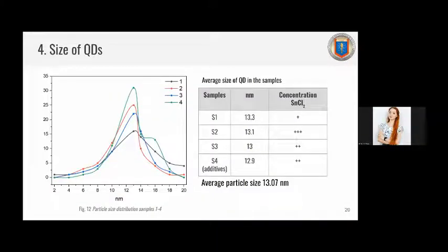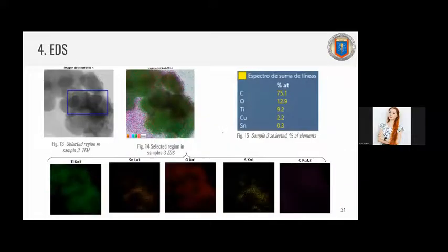Also from TEM, we could analyze the size of the quantum dots, and the size was observed to vary from 2 nanometers to 20 nanometers, with the average size of all 4 samples around 13 nanometers. Also, energy dispersive X-ray spectroscopy, EDS, was done when doing TEM microscopy.